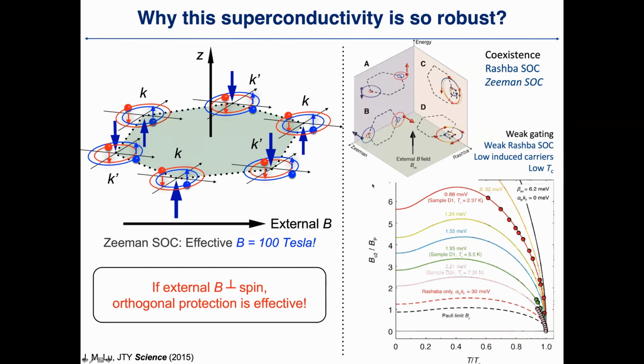But in our system, we also have an electric field applied, so that not only this Zeeman field, which is actually this configuration, we also have this Rashba interaction due to the electric field applied at the surface. Then the Rashba interaction is somehow coupled with the external field when the spin is parallel to the external field in these two cases. And with increased gate voltage, we are actually having a larger coupling between them. So with increased gate voltage, we are also having a higher TC.